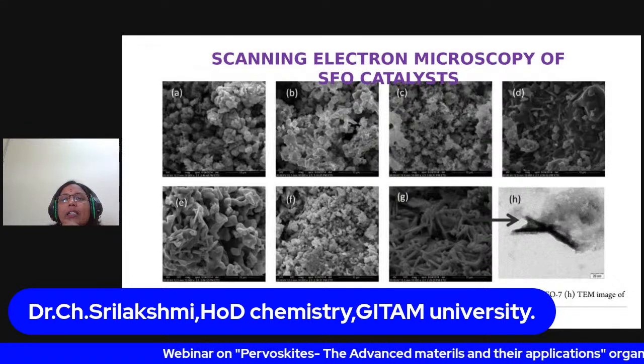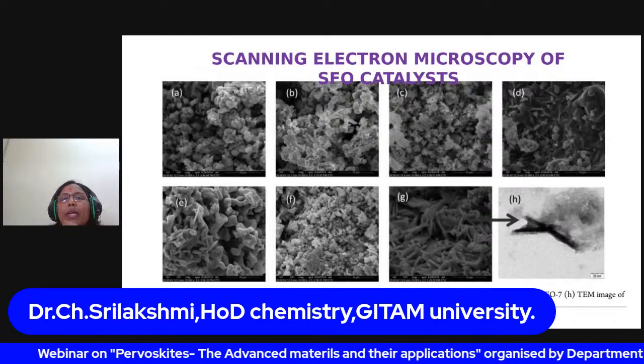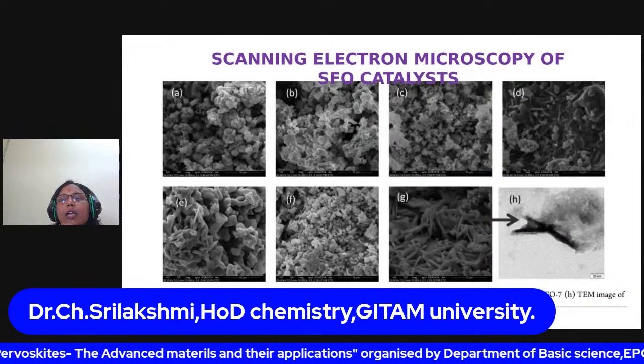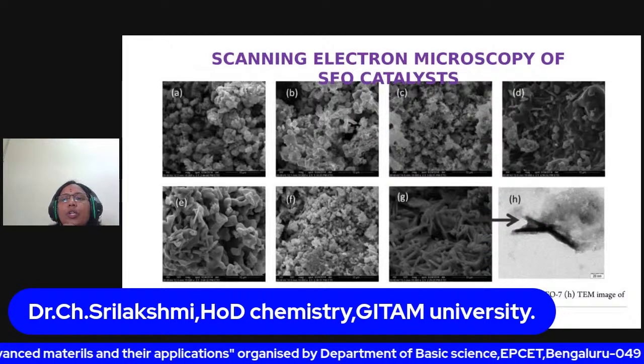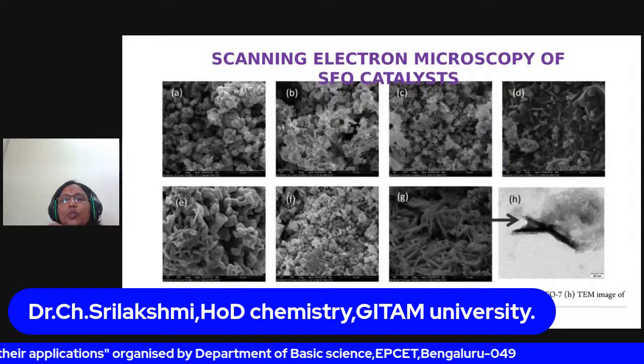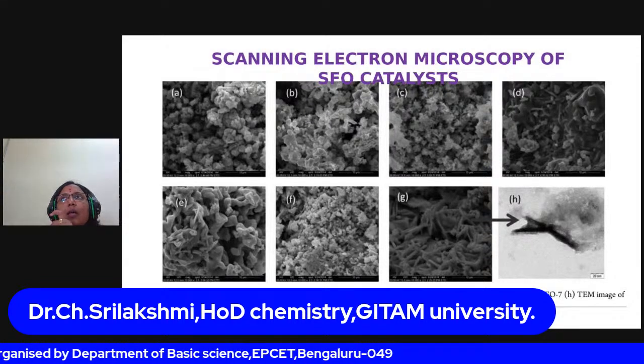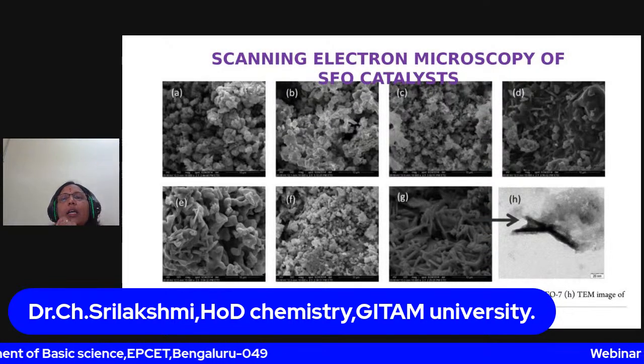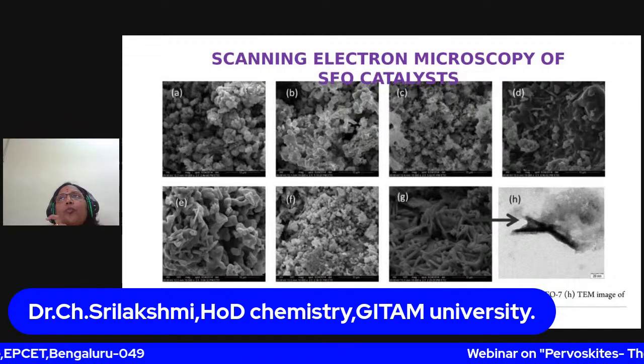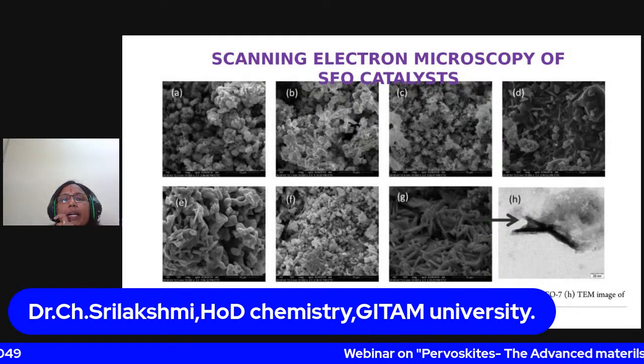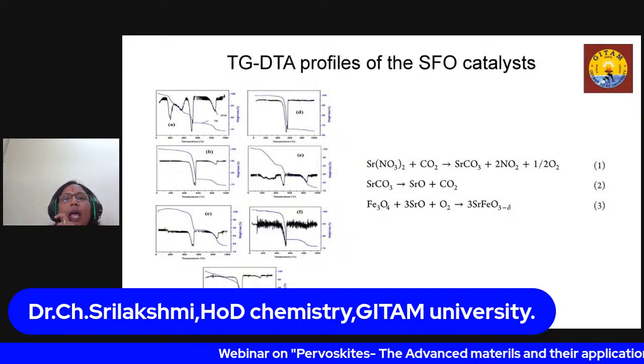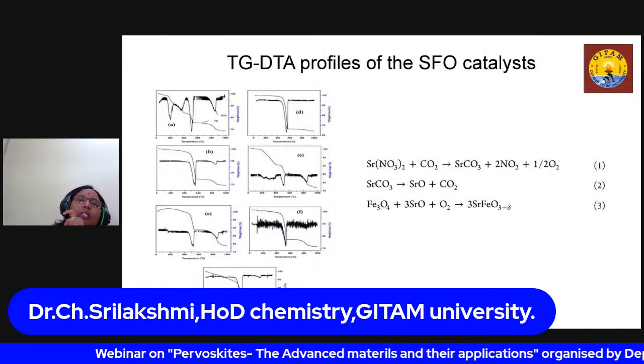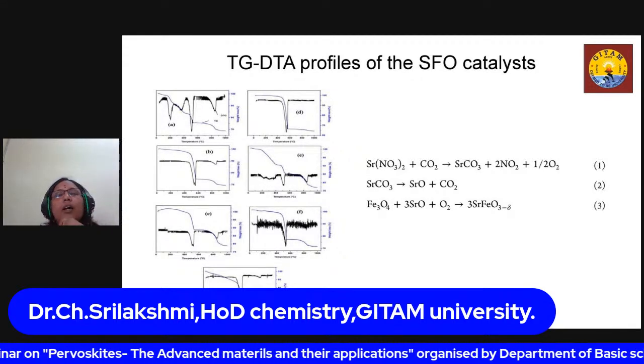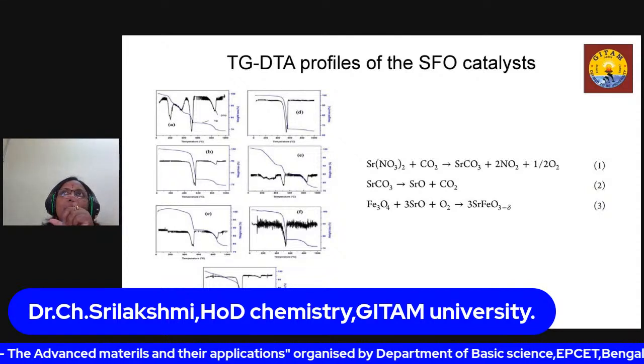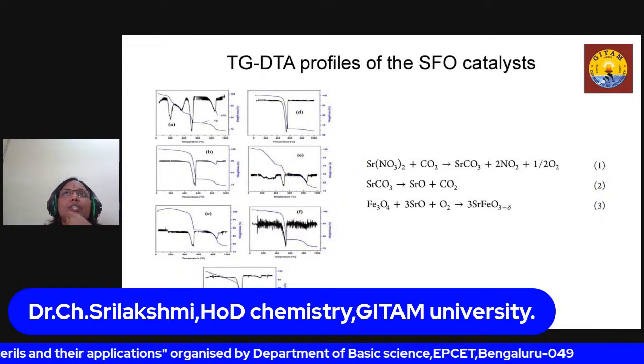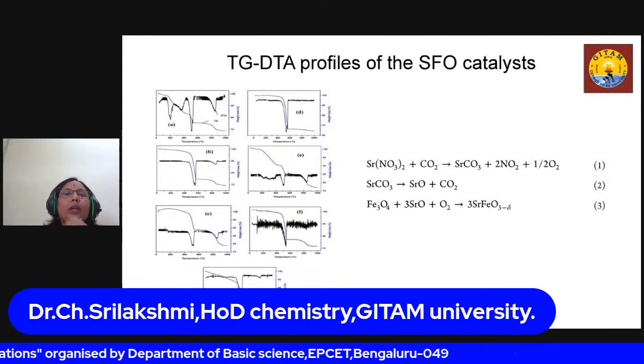These are the same images, whereas we have confirmed the change in morphology by analyzing the sample using transmission electron microscopy. So this confirms that the last sample, prepared using all three fuels, has a different morphology, which is a hexagonal plate-like morphology. And TG-DTA profiles show how this compound transforms. As I showed you, one is stability, and the phase transformation temperature we can identify from the thermal analysis.